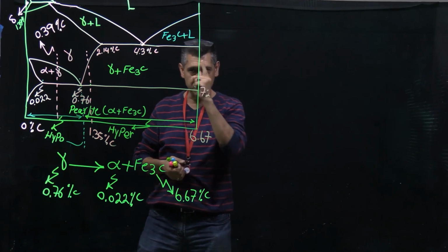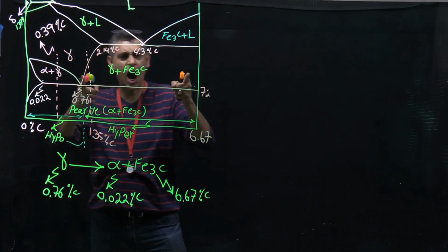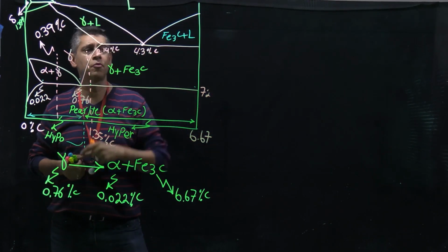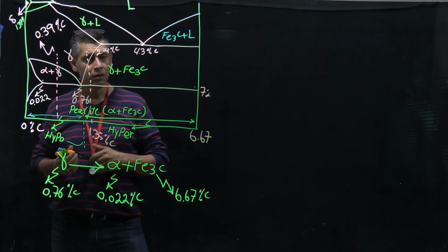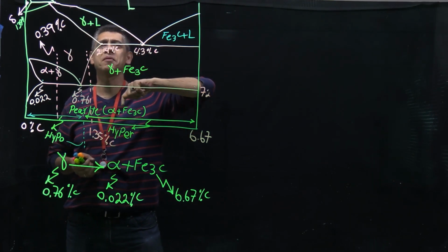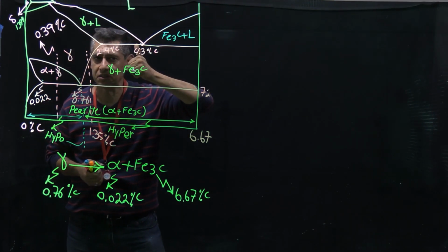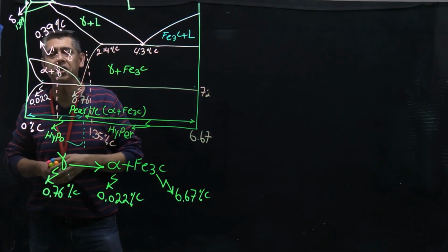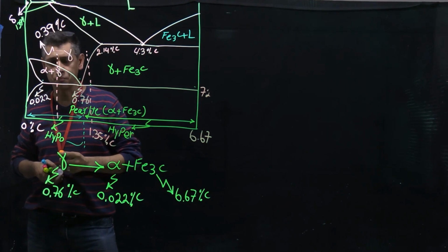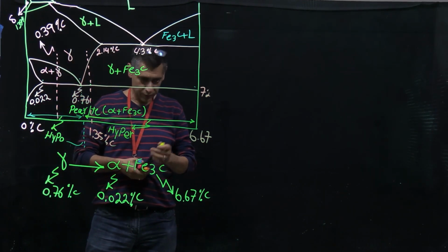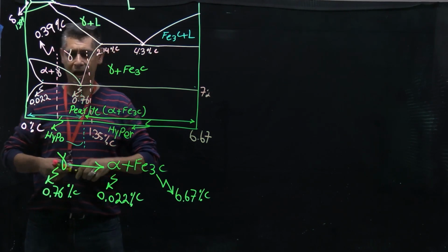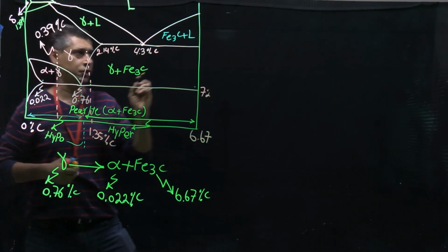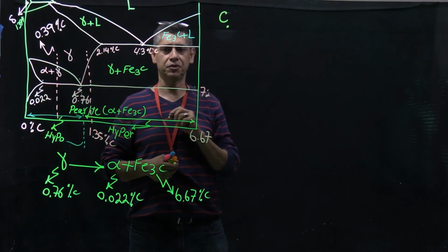So obviously, if I'm in hyper and I remain in hyper by decreasing the carbon content, the cementite, which is the primary phase's mass fraction, decreases, not increases, because cementite has more carbon. I must be in hypoeutectoid. So, assuming that I am on this line and I don't know my carbon content, the carbon content is C sub 0, unknown.